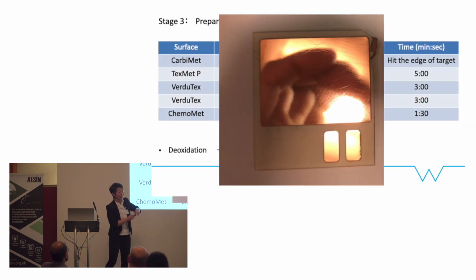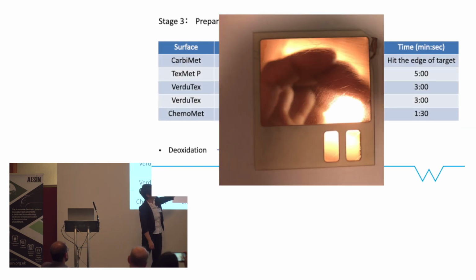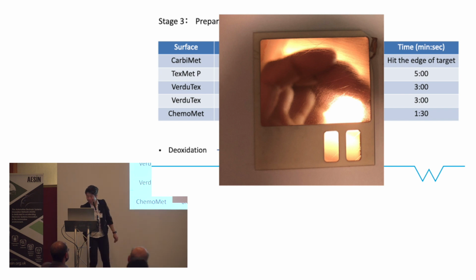to polish a DBC. And then you need to deoxidize, and then you need to put it into sulfuric acid for 5 minutes and wash it with deionized water for another 3 minutes, and then take an ultrasonic bath for another 3 minutes. It will become very shiny, like a mirror, as shown here. This is my hand. I know it's not clear, but this is the dirty one, and after all the steps, the shiny one.